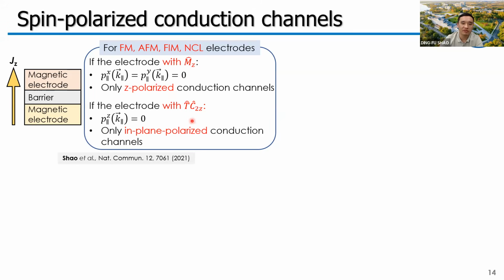But if we have a time reversal plus a twofold rotation around the z direction, the conduction channels can have only the in-plane spin polarization. But if we do not have these two symmetry operations, the conduction channels can have all the spin components. These symmetry arguments work not only for collinear antiferromagnets, but also for other types of magnetic materials.